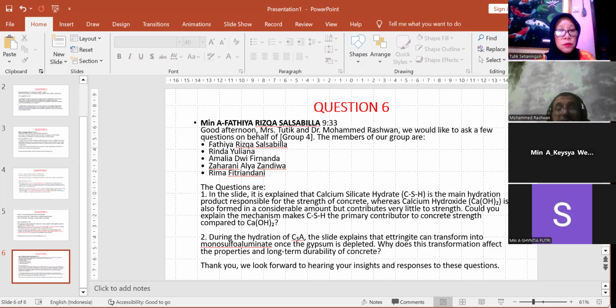The hydration of C3A takes place in two steps. First step, C3A reacts with sulfate. The source of sulfate in cement is gypsum. So C3A reacts with gypsum or sulfate, plus water, and produces what? Ettringite. This phase is very harmful, but if it is produced in the early stage when the paste is plastic, not hardened, there is no worry from the ettringite produced in the early stage.